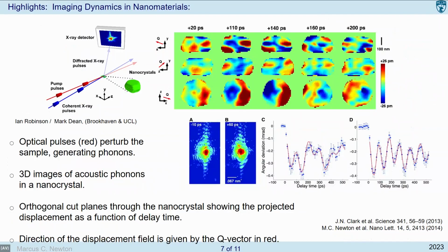Okay, so moving on to imaging dynamics in nanomaterials. Here, this work mostly focuses on CDI, so Bragg CDI imaging of a single nanocrystal. What they've done here is pump with an 800 nanometer laser and probe with the X-rays, and perform a diffraction experiment looking at various diffraction patterns in 3 dimensions as a function of time delay on a single crystal, and then reconstruct the result. So you can see the reconstructed crystals here as a function of time delay, and they're also able to observe acoustic phonon modes as a result. So you can see the different acoustic modes here.